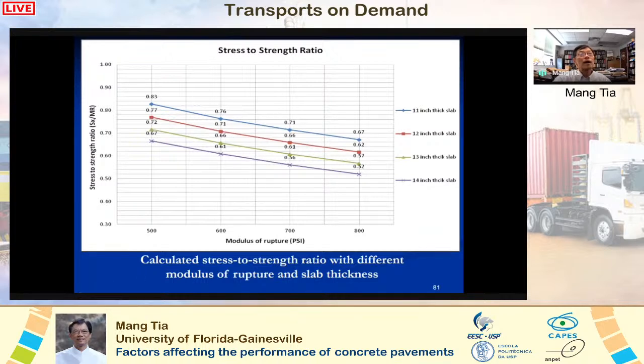And so from the plot, it can be seen that we have a concrete made with the same aggregate. Increasing the modulus of rupture of the concrete will reduce the stress to strength ratio and thus improve the performance of the concrete pavement. Didn't we already conclude that? Well, we concluded that from the MEPDG analysis. Now we conclude it from the critical stress analysis.